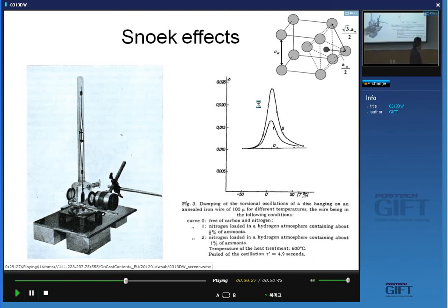This is a very typical phenomenon in terms of physical metallurgy, but unfortunately, the automobile industry does not like that kind of phenomenon, because when you get this yield point elongation and do forming, there is a defect called stretcher strain, and because it is regarded as a defect in the automobile industry, they really do not like that.